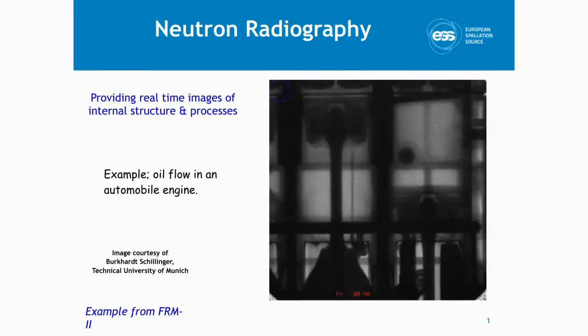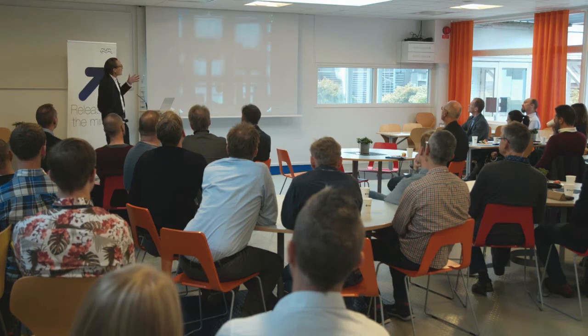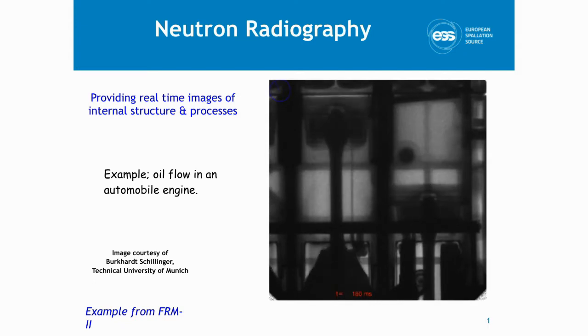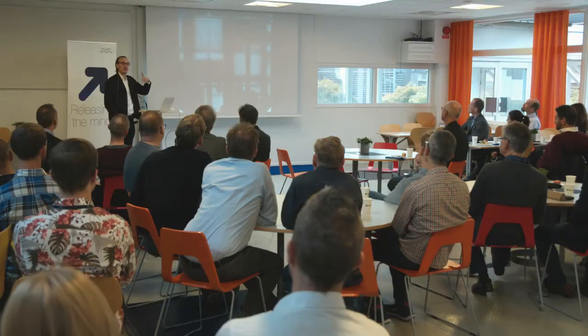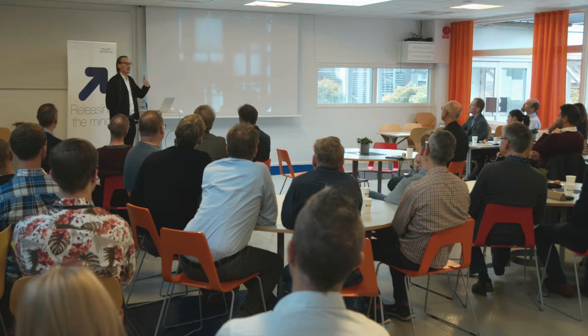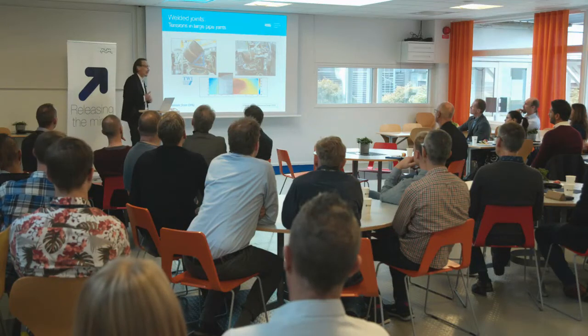Here is a motor from BMW in Garching being measured with neutrons — the research project aims to study lubrication in this motor. What you see in black is not metal, it's oil: where the oil is, and you can even see oil droplets moving in the image. This works because neutrons are neutral and pass through the heavy motor, seeing the light elements inside. In another example, an Australian research project on pipelines used neutrons to study the tension and structure of welds, assuring that the correct annealing process was in place so the weld would not fail later in service.